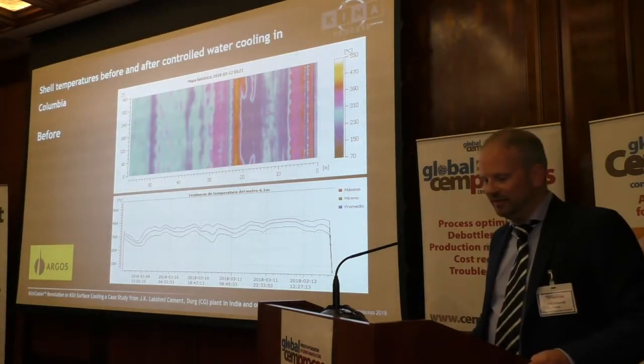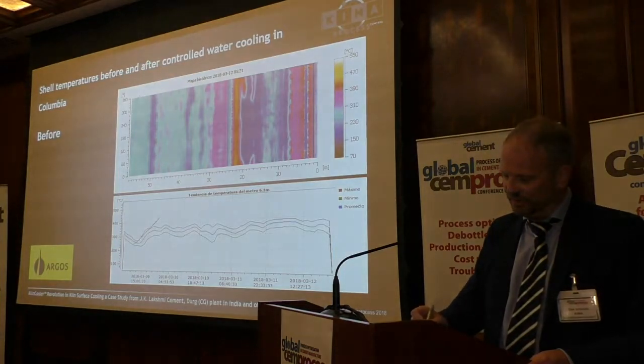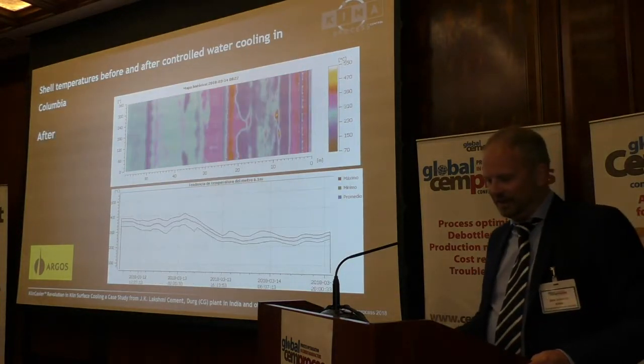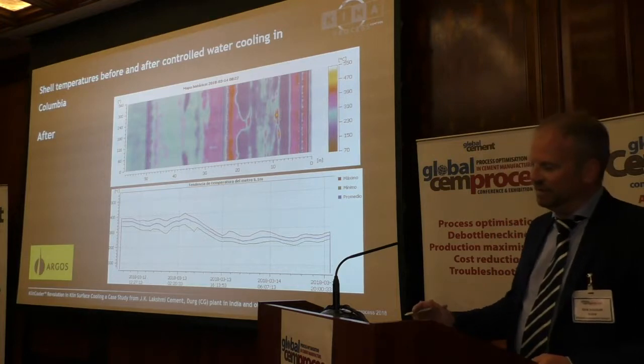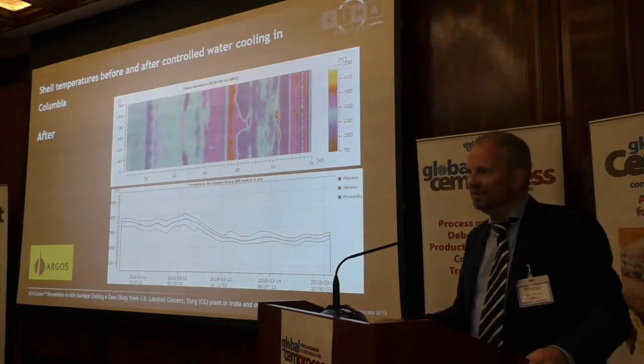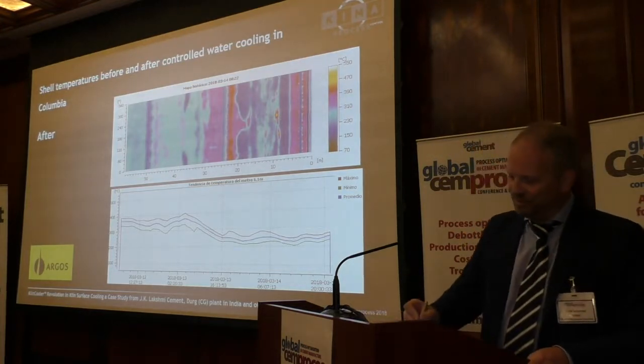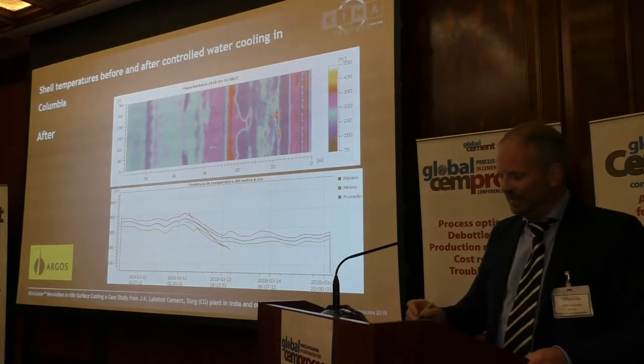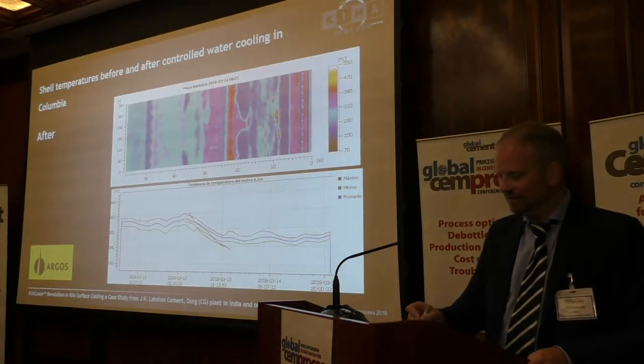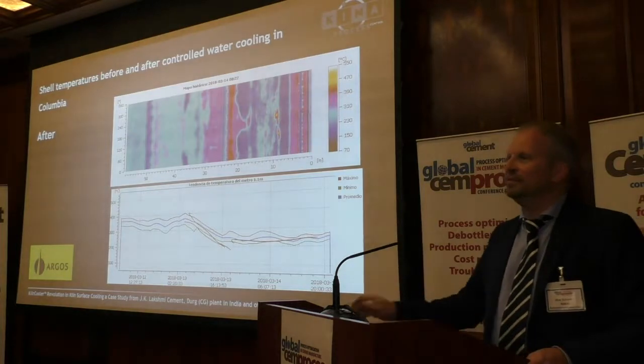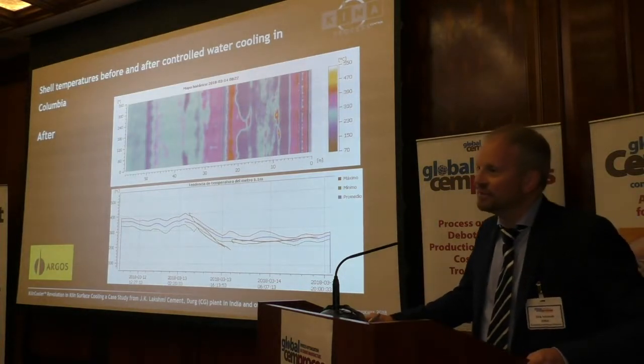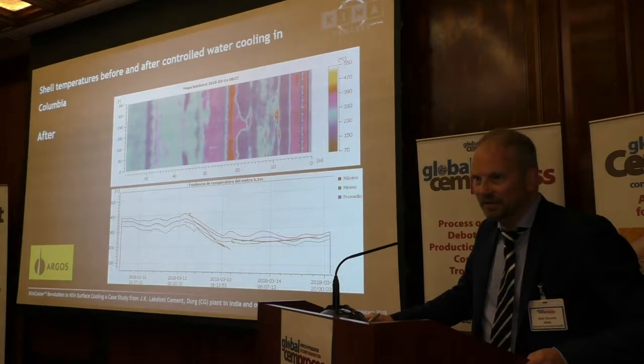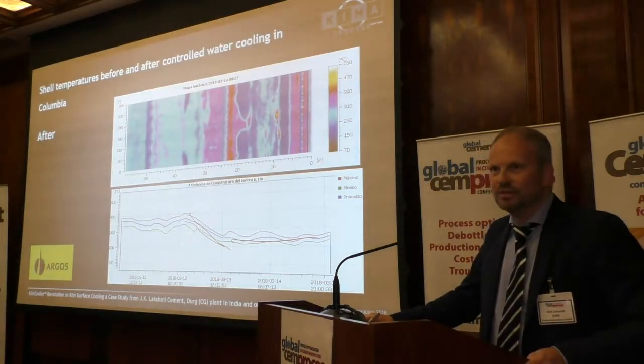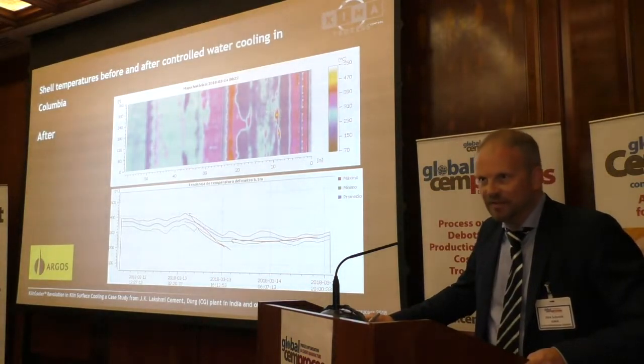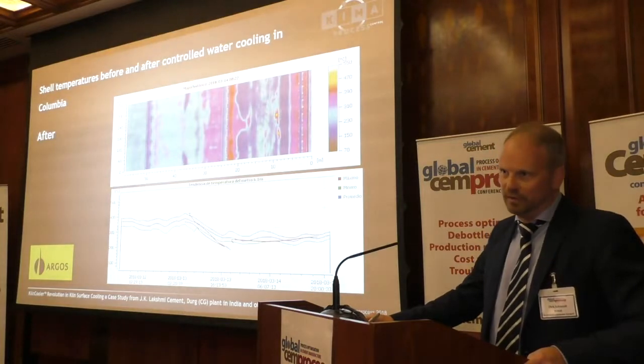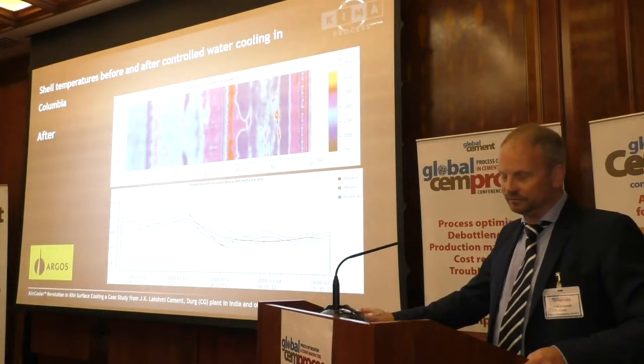You see a relatively high temperature profile from here. And when they switched on the KilnCooler, now look, you see immediately the temperatures go down, and what you see here is exactly what we have seen yesterday from advanced process control. This is, of course, something which is unbelievable and never seen before. We control the kiln shell temperature.